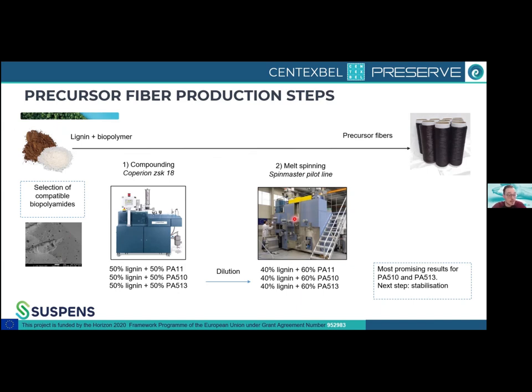Another thing that is important to mention is, like I said, we use the bio-based polyamides as a mixer with the lignin, but it is also important to note that there are different compatibilities with the bio-based polyamides. Especially you have polyamide 6, you have polyamide 11, 510, etc., and we have tried to use all of these different ones, and then the most promising ones we took out were the polyamide 510 and also the 513.